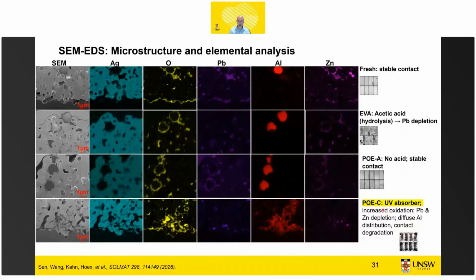what is attacking. So this UV absorber actually attacks the main frit components, so that's lead and zinc oxide, and also it reacted strongly with the aluminium, which was still present in that paste. So that resulted in the contact degradation. And that's what we often see, that whenever we have a reaction with the metallization, it's the frit components that are being affected, being corroded. And typically, if the corrosion reaches the interface, that's when we see this strong failure mode. But it also means that initially, the degradation can be eating through your contacts and you would not see anything. It's only when it can reach the interface that you see the degradation. So this could be a degradation mode that would only pop up after 5-10 years in the field.